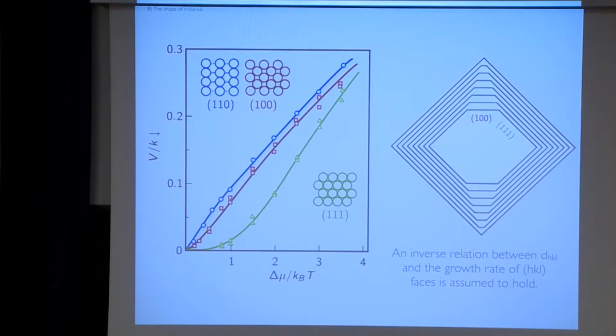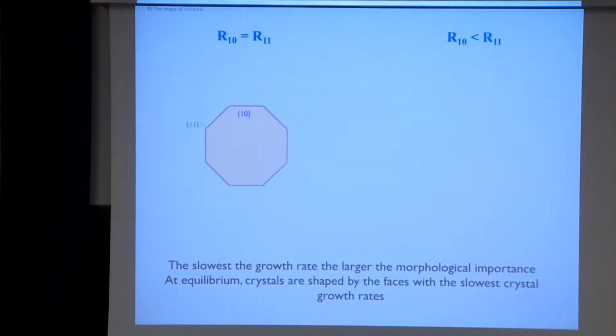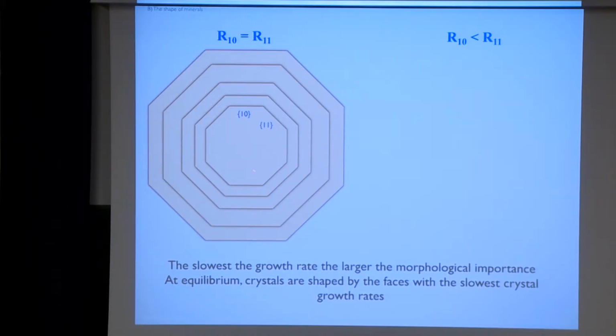So the final shape of a crystal depends, as I told you, on the relative growth rate of the faces formed in a crystal. I will show you just a simple case, to show that the faces that appear on a single crystal are the faces with the lowest growth rate. Okay, so you have this initial two-dimensional crystal, with one (11) face and one (10) face. Both growing with the same rate, and therefore finally you have the same shape, the original shape.